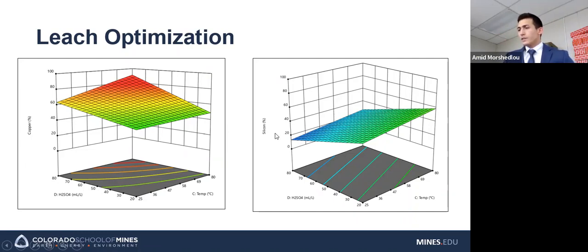And so what we can see is as we increase temperature, copper recovery increases, right? When we go from 25 degrees Celsius to 80 degrees Celsius, we see a slight increase, but it's not all that much. Same thing as we increase sulfuric acid concentration. And that sort of makes sense intrinsically. More acid, we can dissolve more copper. Revelating, I know. And we can also see that by increasing both simultaneously, we can push up copper recovery even higher, which is what we want to do.